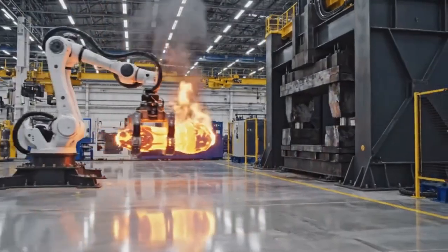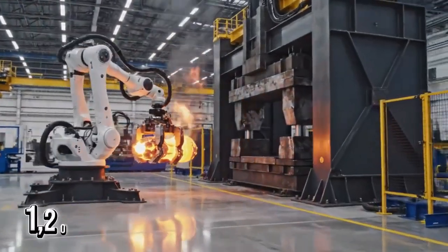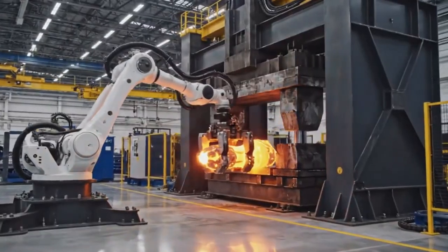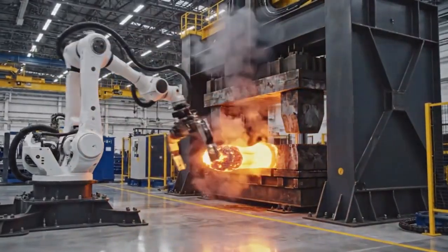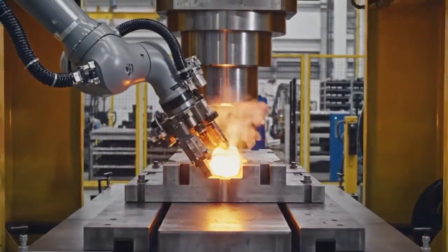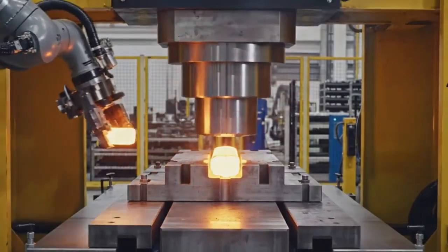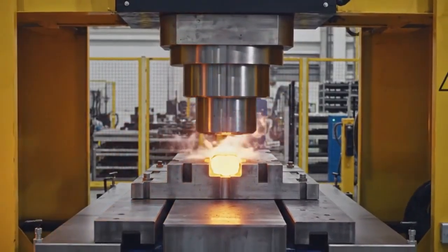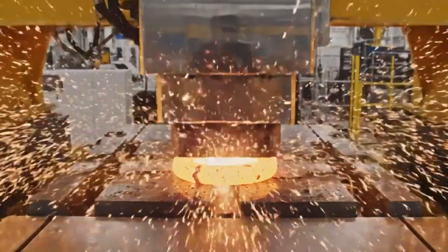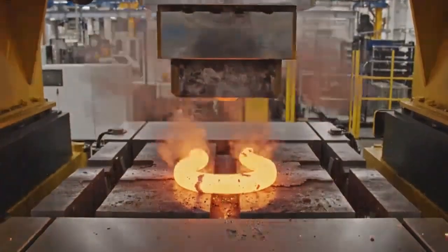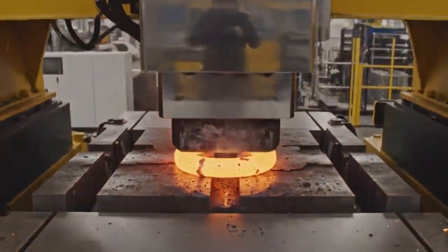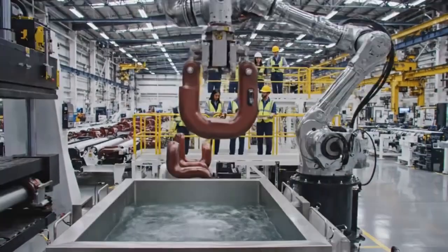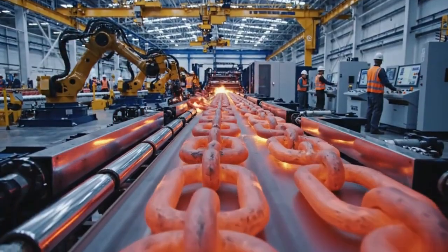In the forging hall, billets are reheated to around 1,200 degrees Celsius in tunnel furnaces. The steel becomes soft enough to bend under extreme pressure. Automated machines wrap each heated billet around a mandrel, forming the oval shape of a chain link. The link is still open like a C, and the previous link is inserted while hot. Anchor chains are not welded. They are forged link by link in a continuous process.